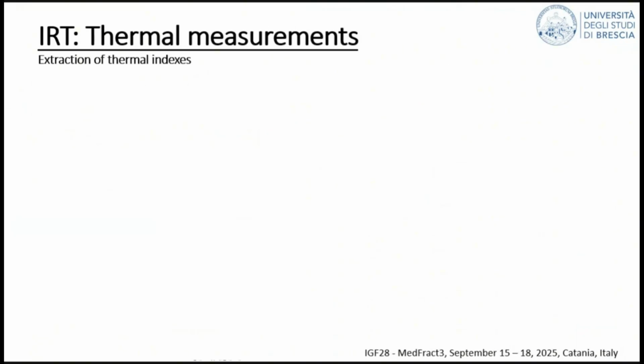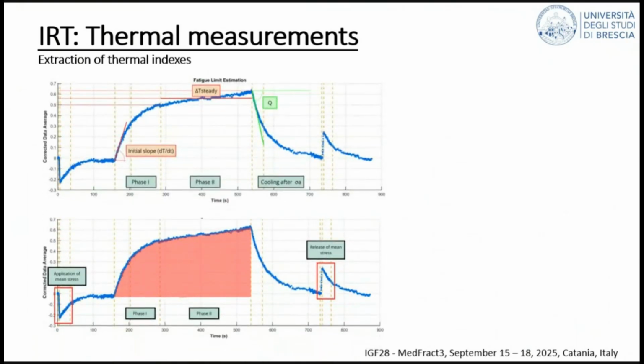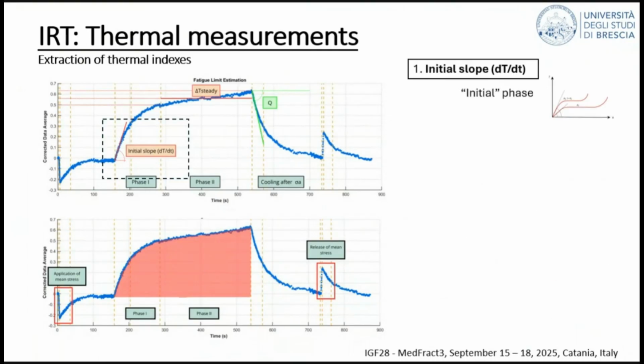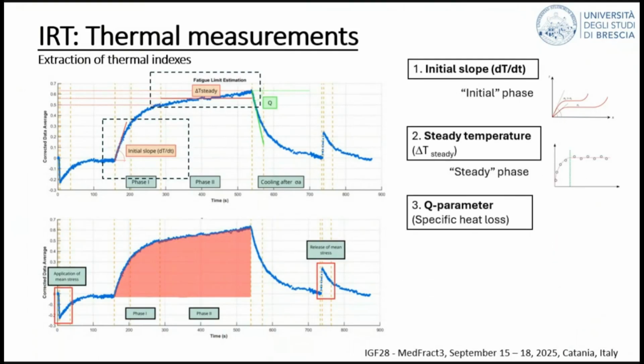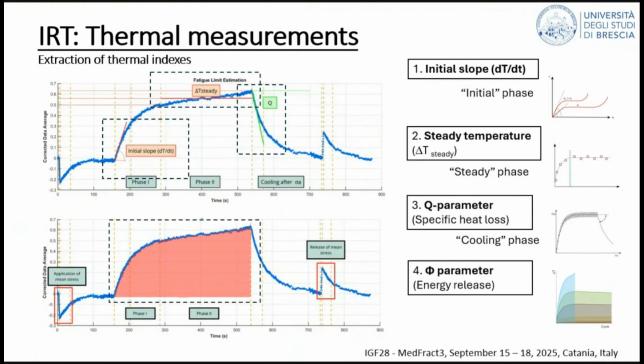Now, from this analysis, we extracted some thermal indexes. Of course, there are multiple options in this field, but in particular, we focused on the initial slope after the beginning of the cycle, on the so-called steady state temperature. Then we extracted the Q parameter, which is related to the specific heat loss, and it can be measured by measuring the slope of the curve when the cyclic loading is stopped. Then we measured the area below the curve to extract an energy parameter.